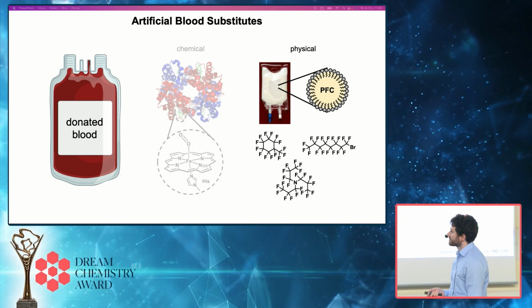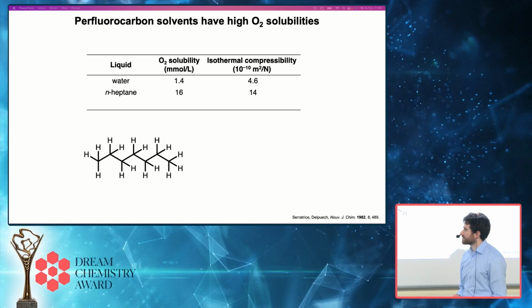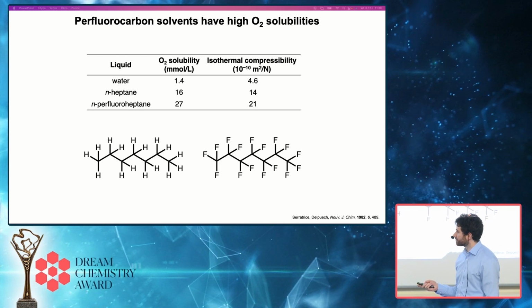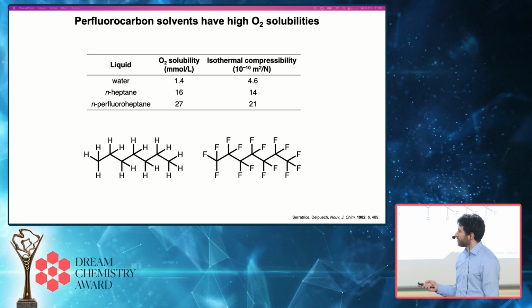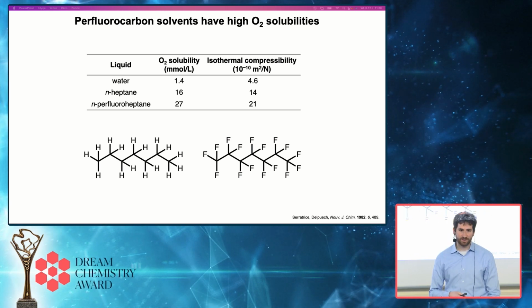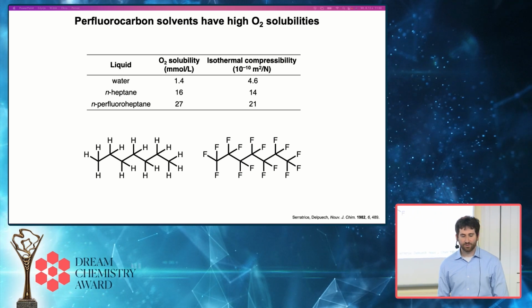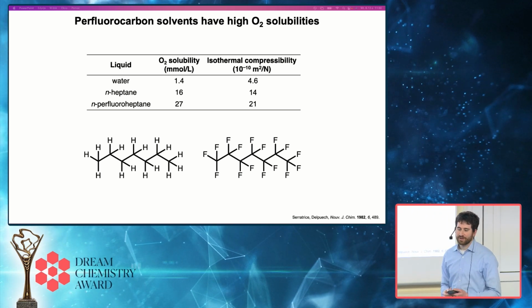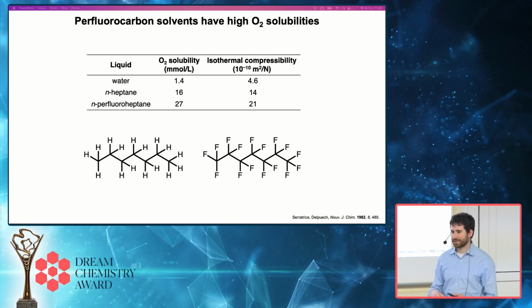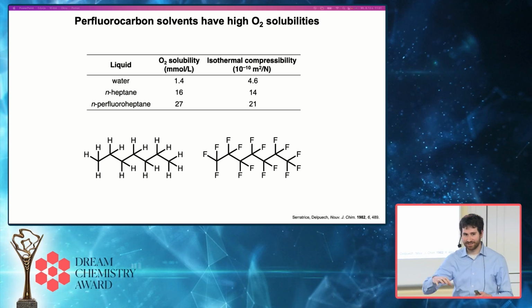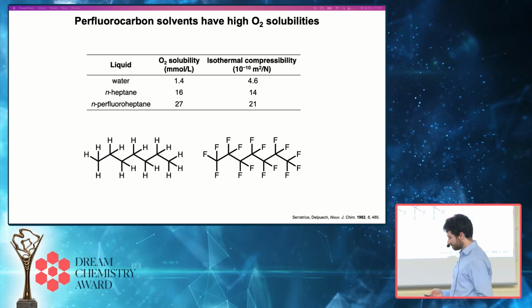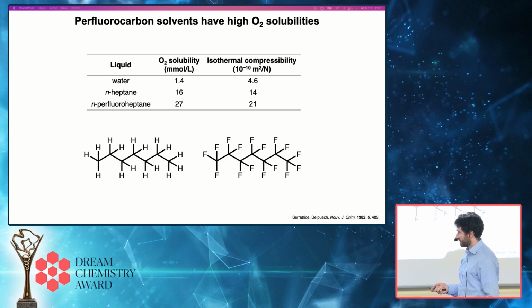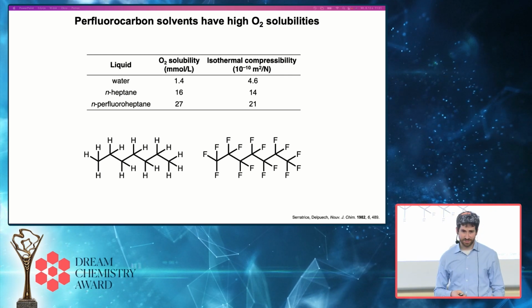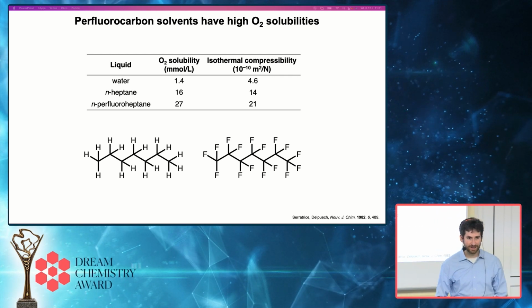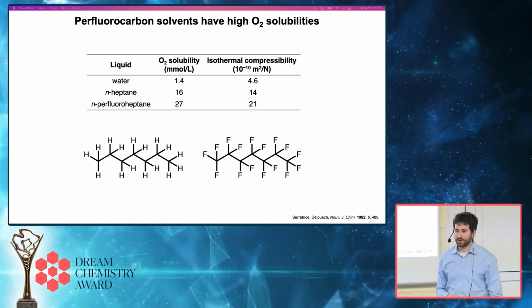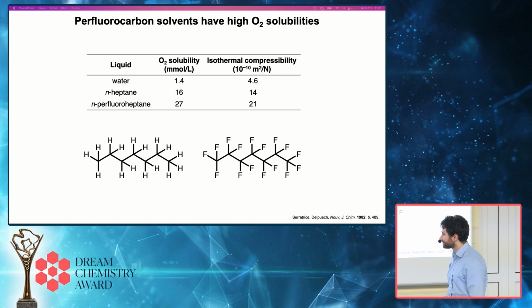So perfluorocarbon liquids, as I mentioned, have much higher oxygen solubilities than neutral organic solvents, as well as than water. So about an order of magnitude more oxygen can be dissolved in a lot of perfluorocarbon liquids compared to water, and that's because perfluorocarbon molecules are very weakly associated, unlike water, and the thermodynamic penalty for dissolving a gas inside the perfluorocarbon is significantly less. And so that's why these were of interest for transporting oxygen. Carbon-fluorine bonds are also really strong, and the body generally doesn't really know what to do with them. And so perfluorocarbons tend to be relatively biocompatible in most cases.